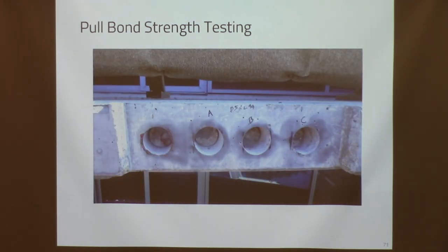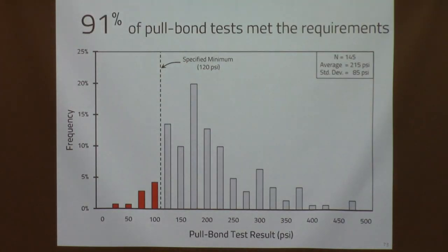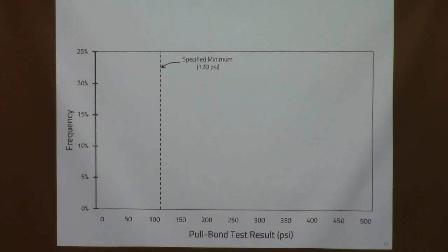And after you do the pull bond test, you can see here the pull bond test has been done. Typically, in an application like this, it's going to fail probably at the bond line. Sometimes it might fail in the existing substrate. Sometimes it fails in repair concrete. Where it fails is reported as part of the test. We had a minimum requirement of 120 psi. You know, a lot of people say it needs to be 175 or 200, but the problem with pull bond tests is there's a lot of variability in the test.